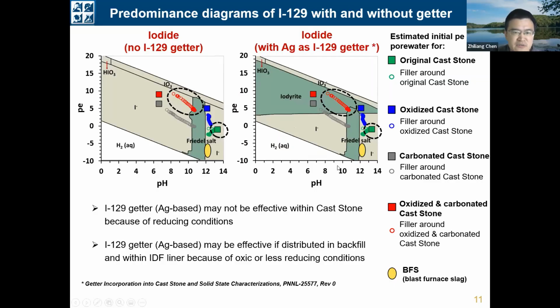And for the iodine, we in fact investigated 2 different systems, and on the left is the results for the system without the iodine getter, and on the right are the results for the system with iodine getter. The getter is assumed as a silver-containing compound because the silver will precipitate together with iodine to stabilize the iodine. So we have some key observations here.